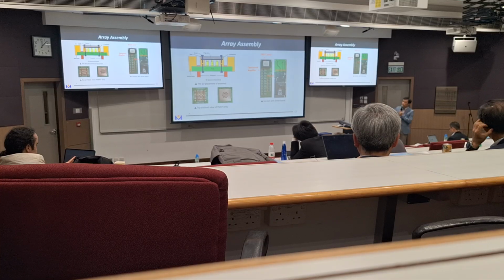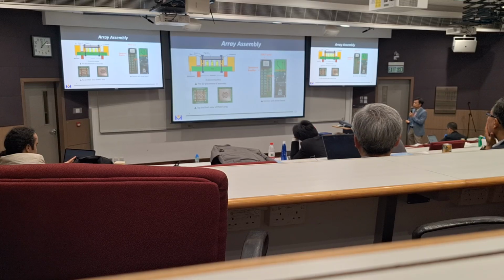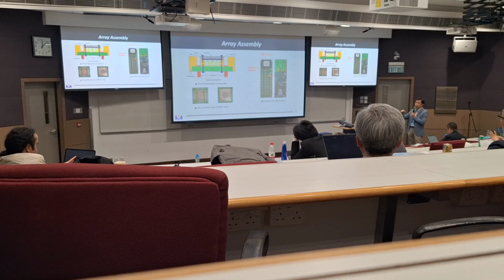And on the right-hand side, you see a driving board we made by ourselves. We're using a chip from Analog Devices. It can generate several channels of sinusoidal sine wave, and we can control the phase difference. And with some operational amplifiers, we can also amplify the signal and use that to drive our piezoelectric transducers.